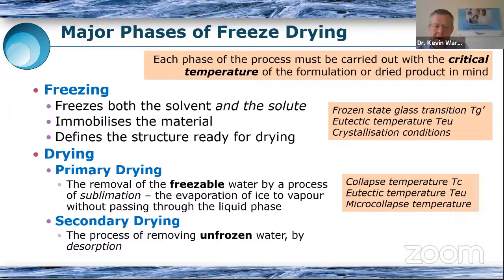And then we come to primary drying. So we divide drying into two segments. The first is primary drying, which is where we remove the freezable water. Now that in itself might be a surprise, to find that maybe not all of the molecules of water that were in our liquid formulation might be freezable, but most of them will be, and we will remove those by a process of sublimation, where we go directly from solid to vapor without passing through the liquid phase. And here we're primarily concerned with the critical temperatures that are the collapse temperature for amorphous or partially amorphous formulations.